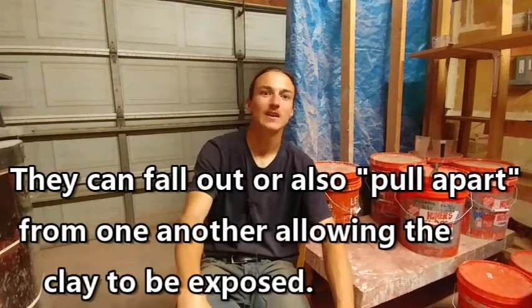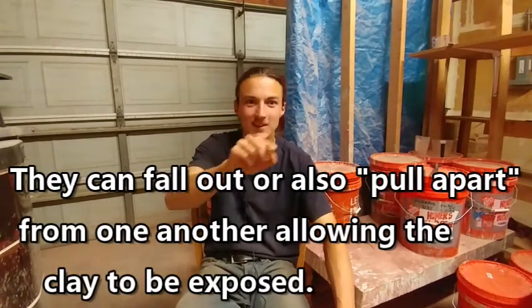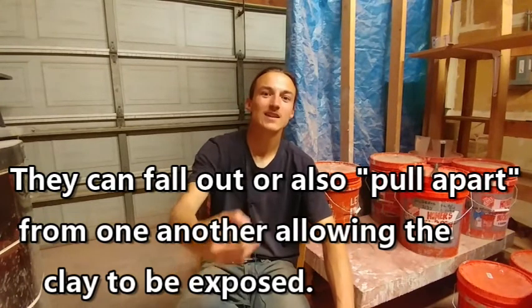This is what causes crawling. If you glaze your mug, let's say, and you apply the glaze and allow it to dry, it takes a long time to dry, there's a lot of water content, and eventually the water content goes away. The glaze shrinks quite a bit during the drying process and cracks. Then let's say you take your finger and try to smooth it out, you put it in the kiln, and then bits of your glaze fall out during the kiln firing. At the end, you start seeing bald spots, areas where it's supposed to be glazed. That is crawling.